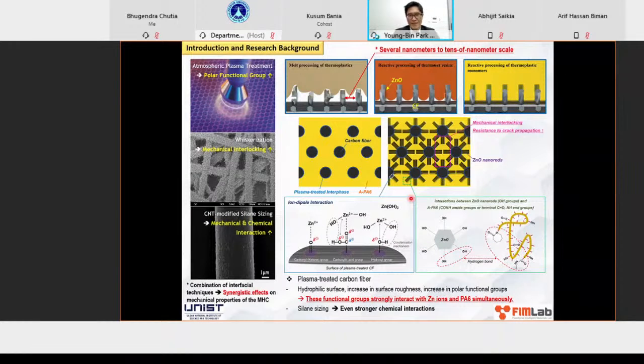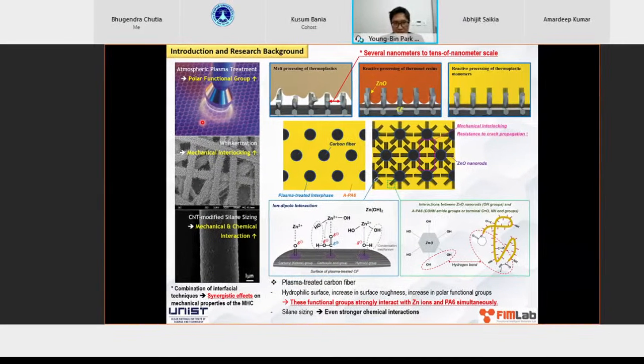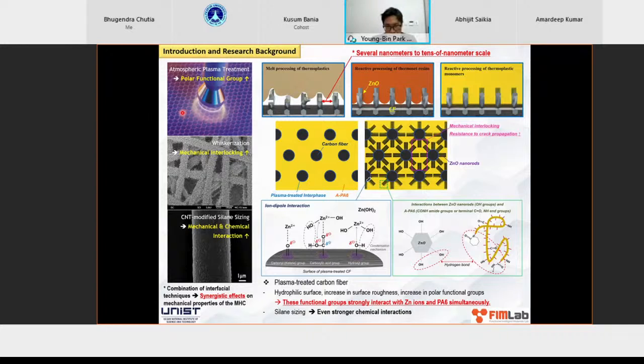There are three main components that are involved in the first topic. First, we surface treated the carbon fiber with plasma, atmospheric plasma, and effectively what this does is plasma treatment creates a hydrophilic surface on the carbon fiber surface. At the same time, it increases the surface roughness. Now, if you have a rough surface on the fiber, then that creates better contact between the fiber and the resin. And the third, most important effect is that it increases the polar functional groups on the fiber.